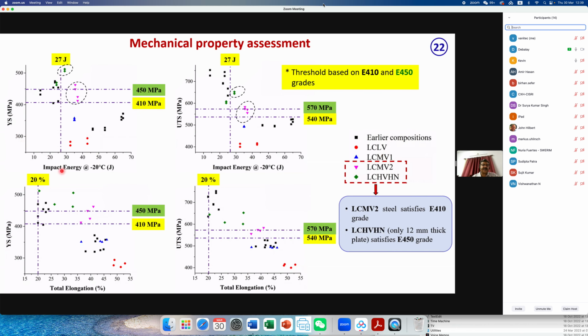So here we are plotting YS versus impact energy. This yellow color is showing 410 grade requirement and green color showing 450 grade requirement. And these are the toughness requirement for these grades. So we find this pink color and green colors are meeting. So these two are meeting from strength, toughness point of view. These two are meeting the 450 requirement. Similarly, strength, elongation, again for 410, 450 required elongation. So here several grades are meeting, 3 grades are meeting the requirement, pink, black as well as green.